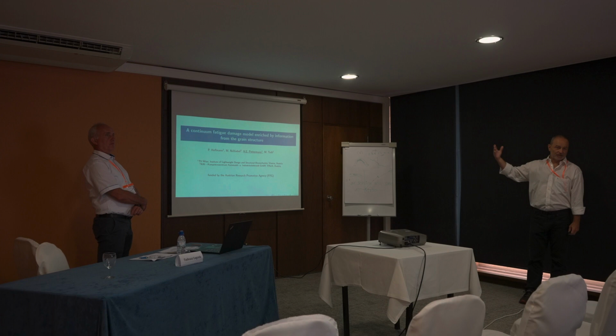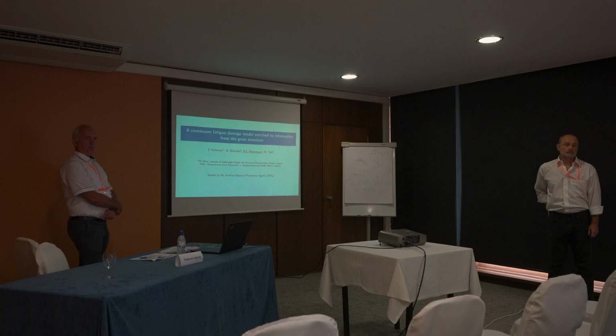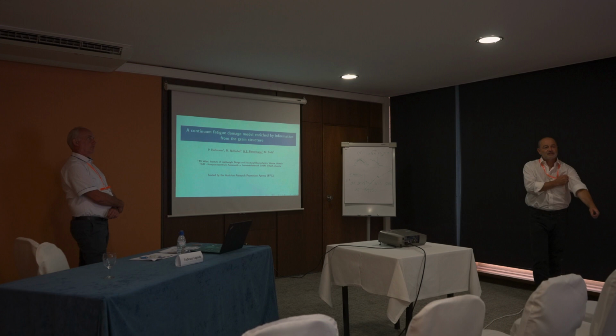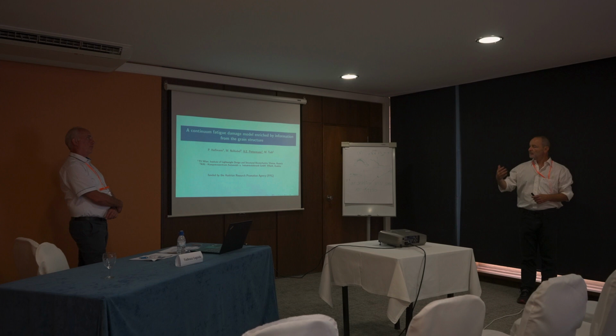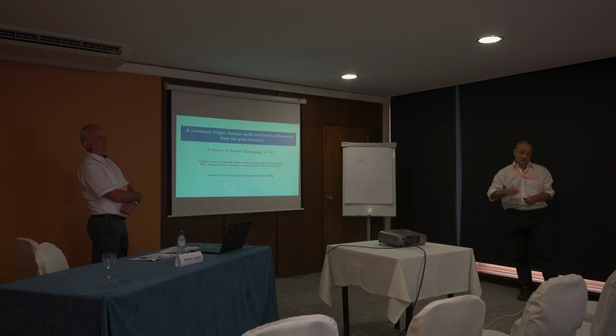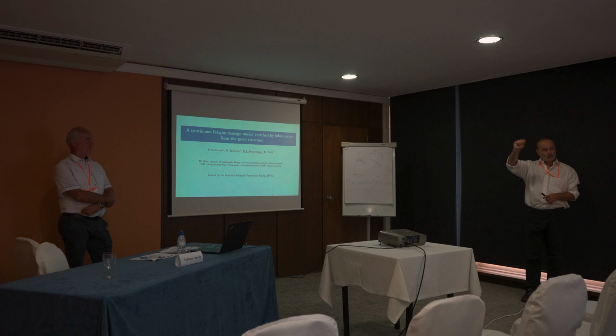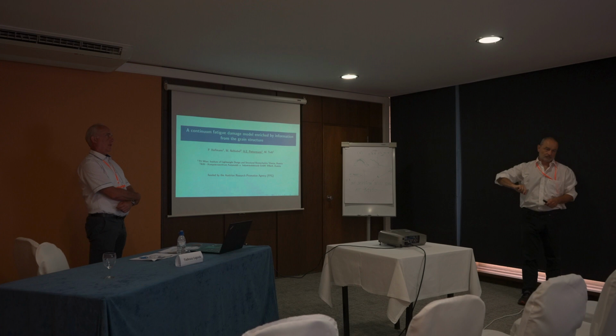But that was what I mean. You could also similarly insert points with another H-parameter along lines that are in the experiment. Yes. We could. We did several initial studies on what is a good way, and at least from the things we tested, this was the most promising. Okay. Typically, if you look at the hot spots, they are located at the grain boundary.